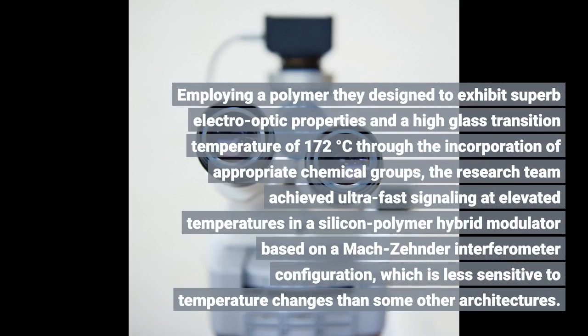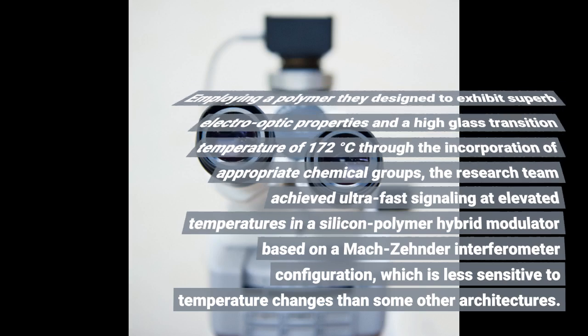Employing a polymer they designed to exhibit superb electro-optic properties and a high glass transition temperature of 172 degrees Celsius through the incorporation of appropriate chemical groups, the research team achieved ultra-fast signaling at elevated temperatures in a silicon-polymer hybrid modulator. In the modulators, composed of multiple layers including the polymer and silicon, an incoming laser beam is split into two arms of equal length.